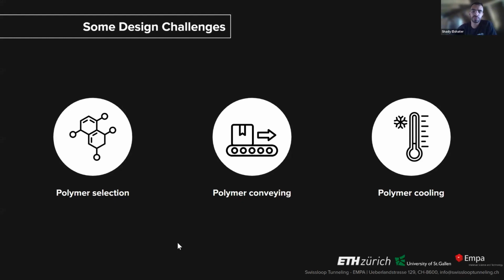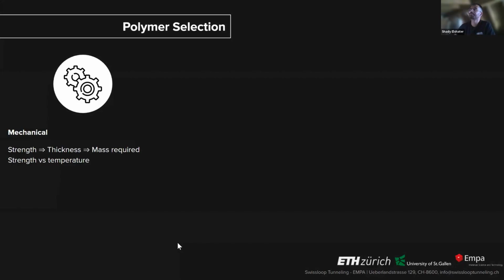So moving on to the design challenges. The first one was really the polymer selection. Then the conveying of this polymer, from the outside of the tunnel up to the extruder, and then the polymer cooling. Starting with the polymer selection, the first part is the mechanical properties. Clearly, the strength of the polymer affects the thickness, hence the mass of polymer required, and that's the main dimensioning factor for the extruder. And then also keeping in mind the relation with temperature of that material, to make sure that once the liner reaches the back of the machine, it's already really solid and well below the glass temperature.